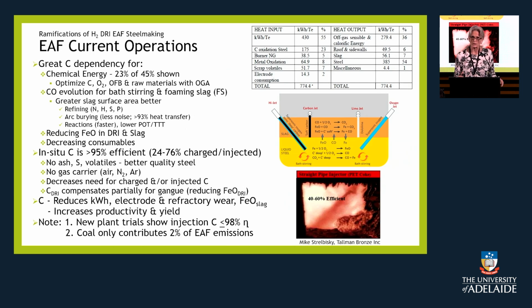The arc furnace operations currently are predominantly based on the chemical energy from carbon, and it can be as high as 25–30% sometimes. And that chart that's up there, I believe it shows 23% of the 45% chemical energy is coming from the carbon. The CO evolution from that carbon in the system is stirring the bath. It's improving the contact between the foamy slag that it creates and the metal. It's cleaning up the steel.